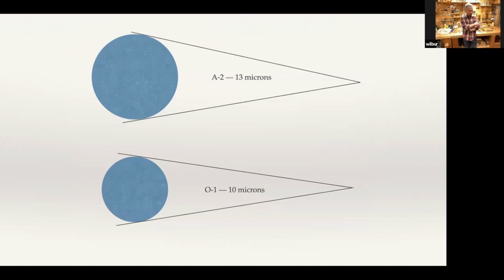I haven't been able to find a reference for that, but I have found a reference to the carbide sizes in Damascus swords, the ones that were made around the year 1000 when the Crusades were going on. They've analyzed those, and the carbides are about 3 microns in diameter. And the process by which Damascus swords are made is pretty much exactly like what I've shown you, the hard layer surrounded by the soft layer and the forge welding and whatnot. So if I take this diagram and I drop in a bunch of 3 micron carbides, that's what you see.